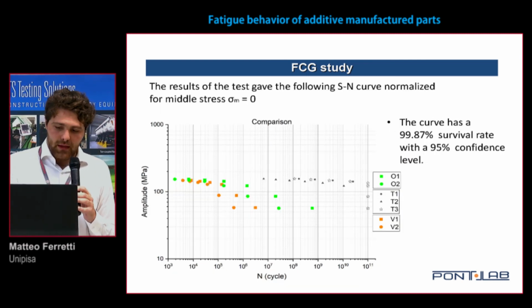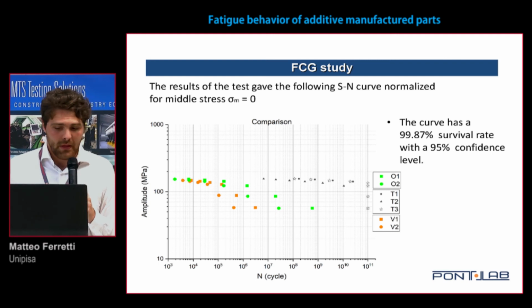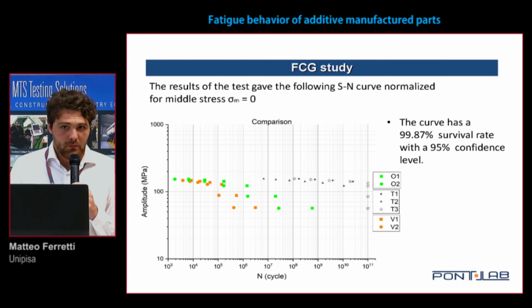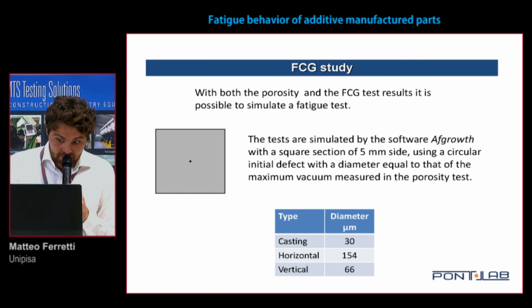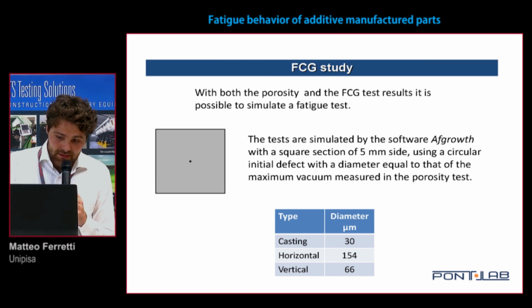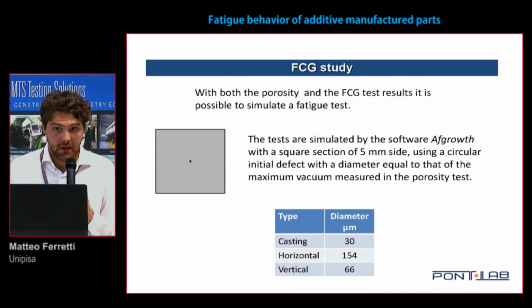The casting specimen has too good a behavior. This fact is caused by the dimension of the initial defect, which is too small, and the model used by AFGROW can't simulate the crack growth from a little defect.